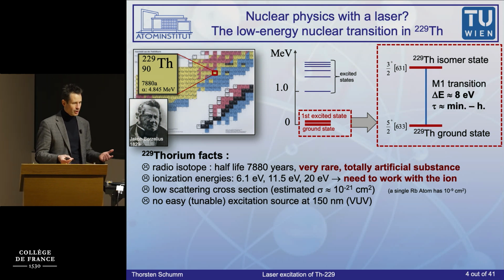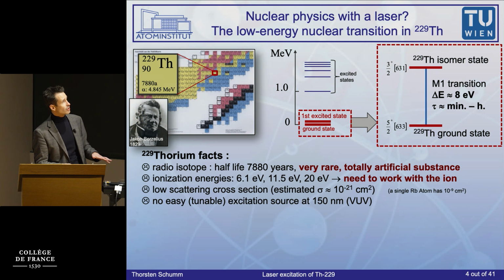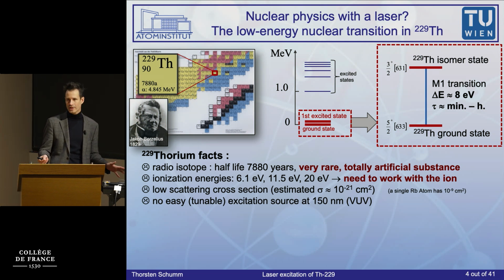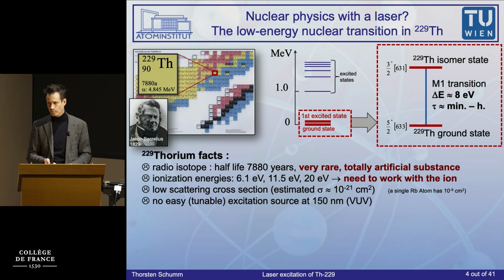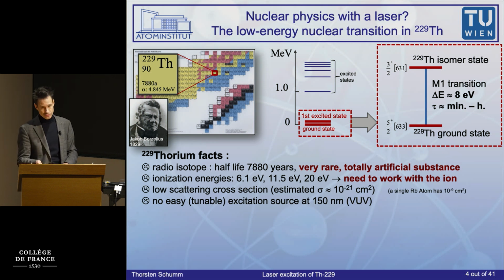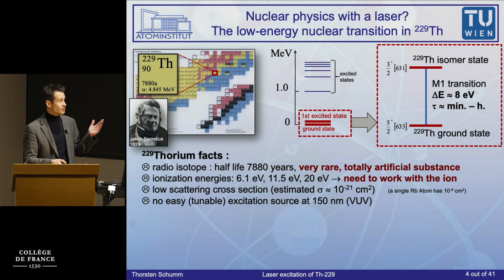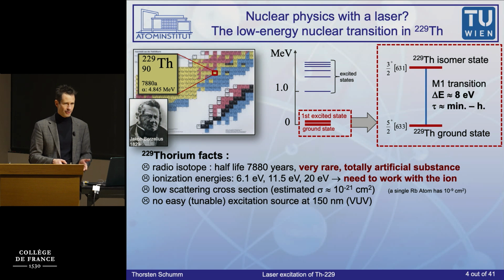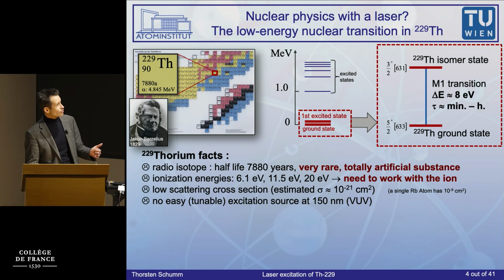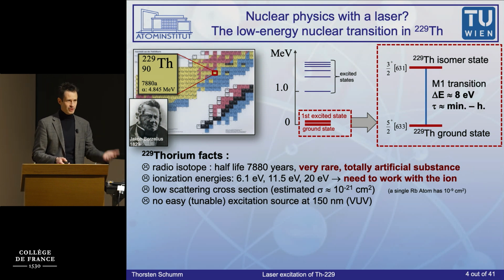So what we will do in the work I'm presenting today is go for a 4+ thorium ion state. 4+ is a radon-like noble gas configuration. It doesn't have electronically excited states which are energetically accessible at 8 electron volts. I already mentioned that the interaction cross-section with light is low. It's significantly lower than any atomic or ionic cross-section. That means not only is it hard to produce 150 nanometers, but even if you have a laser source, it's still very hard to excite this nucleus.